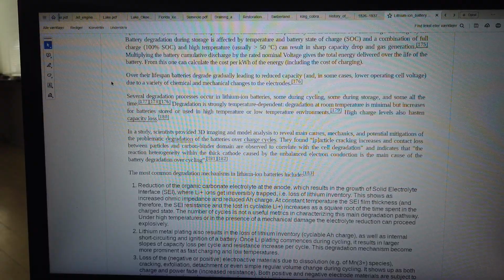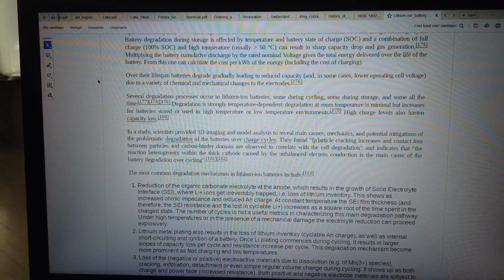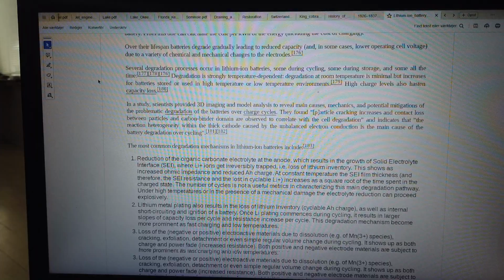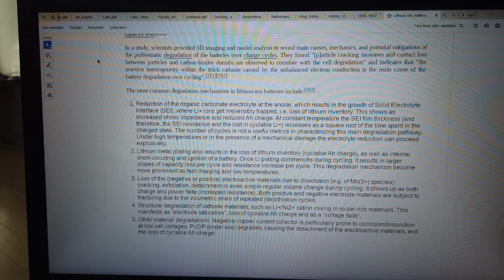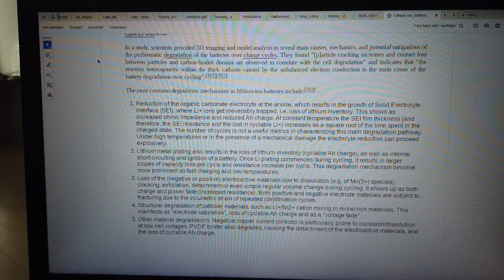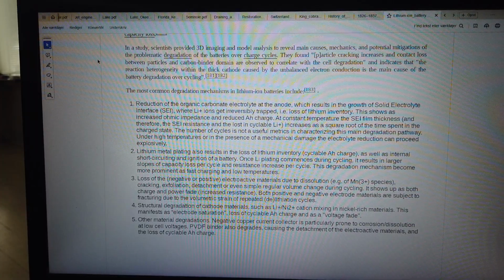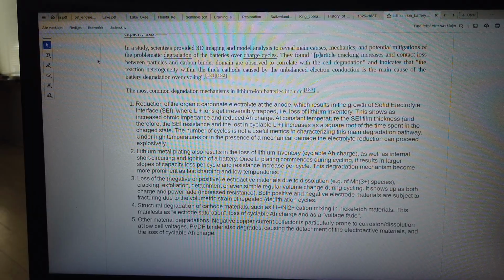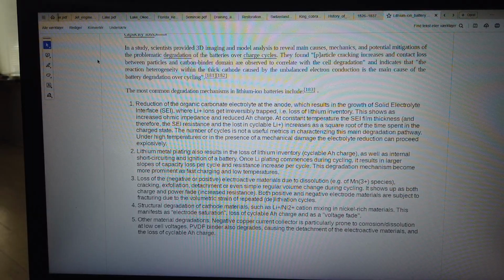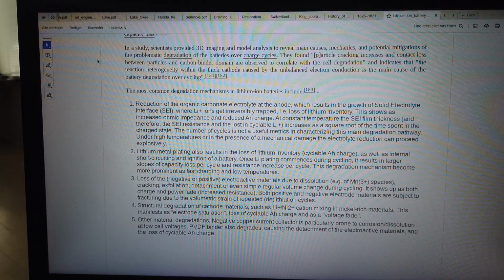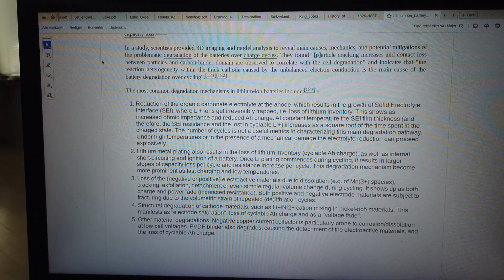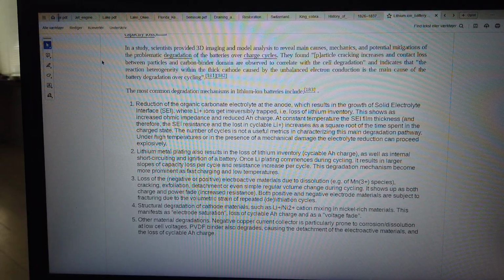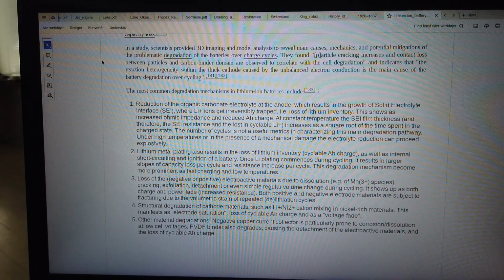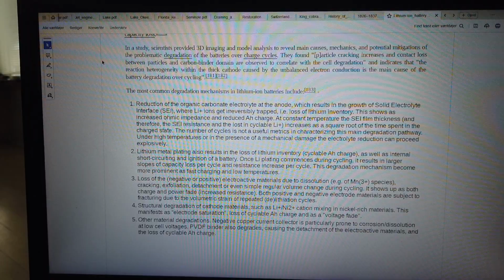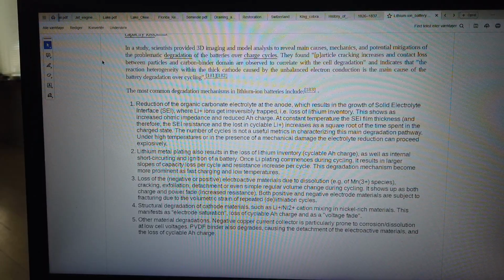In a study, scientists provided 3D imaging and model analysis to reveal main causes, mechanics, and potential mitigations of problematic degradation of the batteries over charge cycles. They found particle cracking increases and contact loss between particles and carbon binder domain are observed to correlate with the cell degradation, and indicates that reaction heterogeneity within the thick cathode caused by the unbalanced electron conduction is the main cause of the battery degradation over cycling.